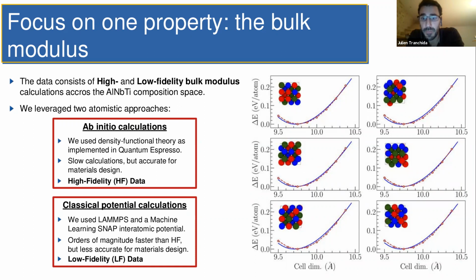So the red dots here are the DFT data, and the blue lines are what the SNAP potential is giving. Because I didn't say that, but the second level of fidelity is going to be given by classical potential calculations. So we use LAMMPS. It's not really molecular dynamics here. We don't run any dynamics. We just compute the energy, basically. So it's a classical potential calculation with the SNAP potential we just developed. Of course, it's much faster. We can do much more evaluations and take better averages, but it's still going to be much lower accuracy than the ab initio calculations. That's going to be the low fidelity data, so basically the blue lines here. And from the same curves for all the compositions, we're going to be able to do the calculation I'm going to show you on the next slide.